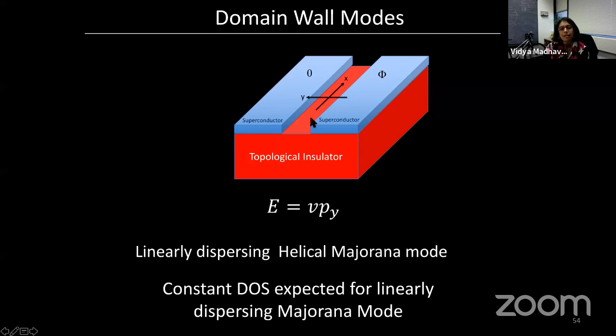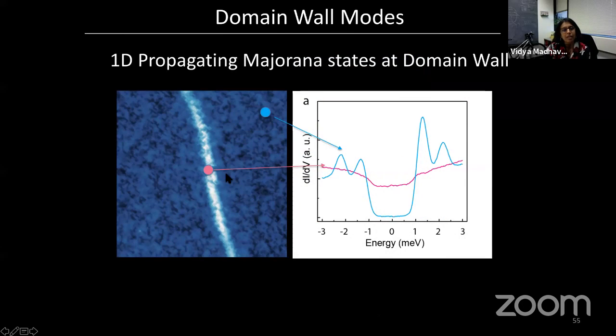The interesting thing is that if you have a one-dimensional system with a linear dispersion, then what you expect to see is a constant density of states. That's exactly what we see. So we believe that the constant density of states we see inside the superconducting gap comes from helical Majorana modes at the domain wall. Vidya?